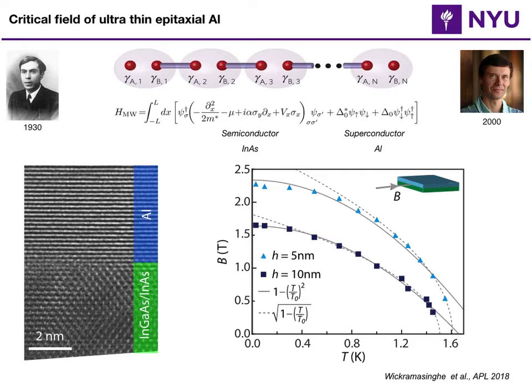And Tedrow and Meservey have shown that once you go to ultra thin films, you can actually get to the Pauli limit of the critical field. So here I'm showing you epitaxial aluminum on indium arsenide films with 5 and 10 nanometer thicknesses. And as you see at, I guess not zero, but millikelvin temperature, the critical field is quite high, right? At 10 nanometers, you get above 1.5 Tesla, and at 5 nanometers, you get above 2 Tesla.